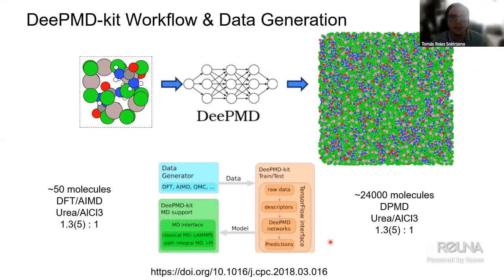PACKMOL basically takes the concentration or number of atoms we estimate based on the composition of experimental electrolytes, meaning in this case 1.3 urea to AlCl3, or 1.5. Then, in a volume of about 10 to 15 angstroms on a side, we estimate how many molecules approximately of urea and the chloroaluminate will be present in a box of that size.